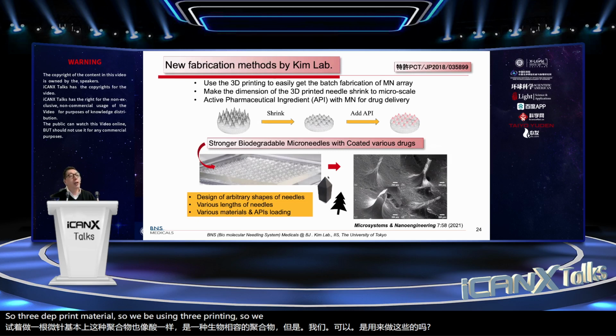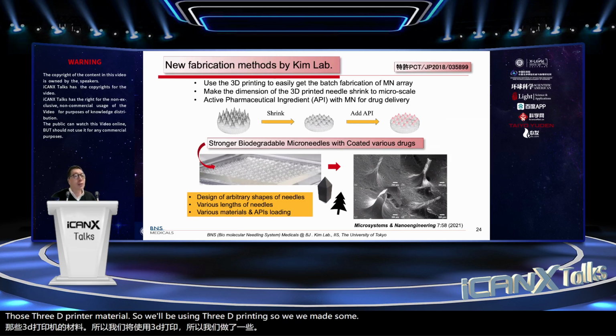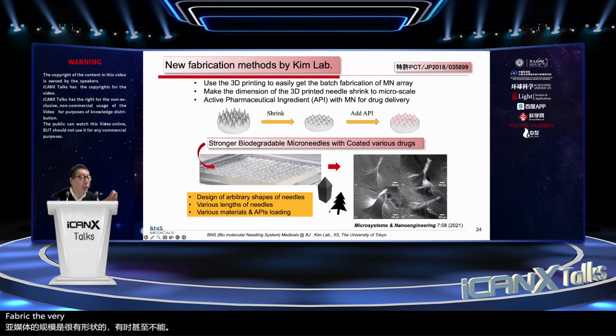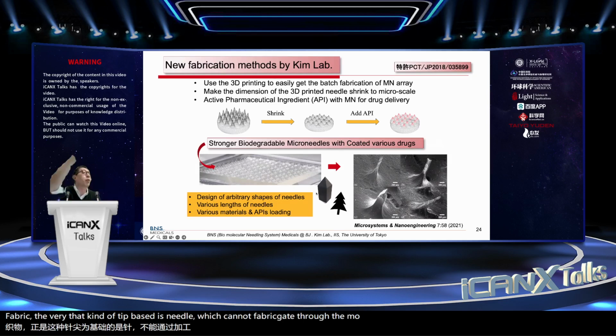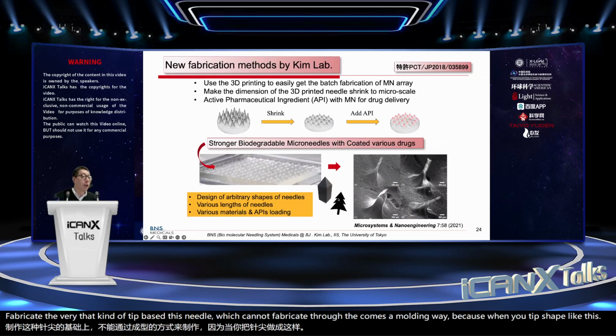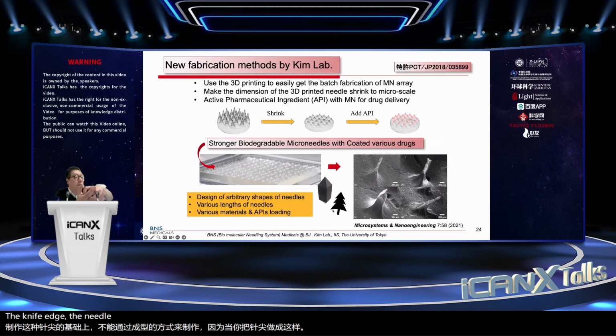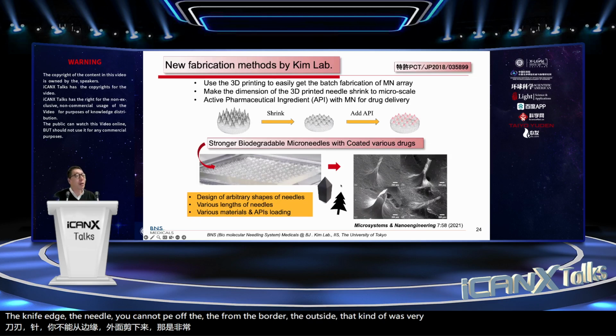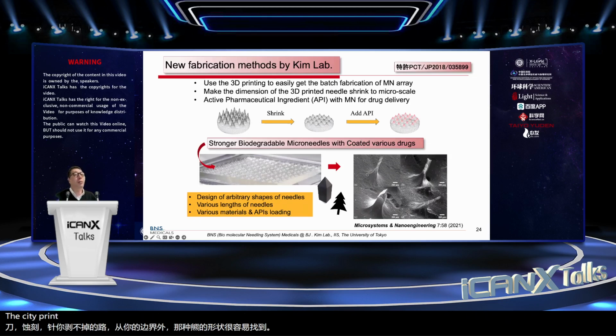So we made sub-milli scale needles of various shapes, even ones which cannot be fabricated with that kind of tip through the conventional molding way, because when you have a tip shape like a knife edge needle, you cannot peel it off from the mold. That kind of barrel shape can easily be fabricated by 3D printing, because we found an isotropic etching condition to reduce this 3D printed barrel-shaped structure to micro scale.